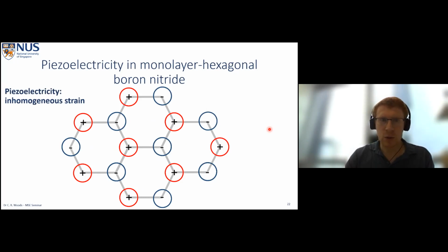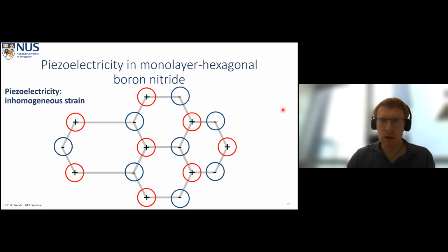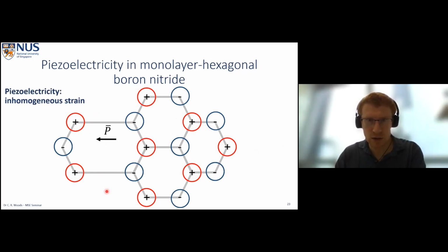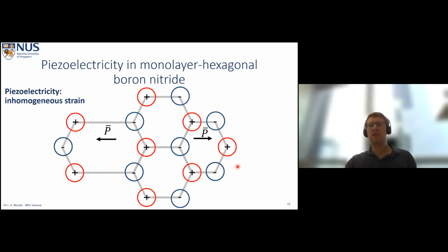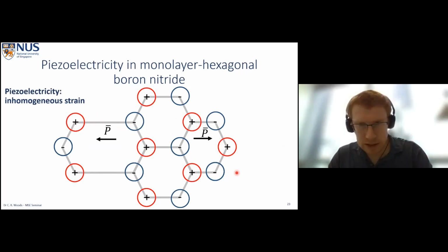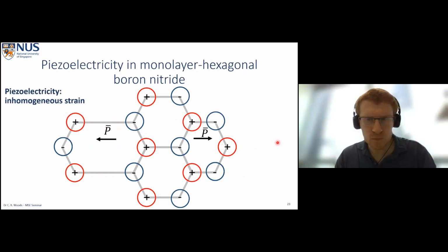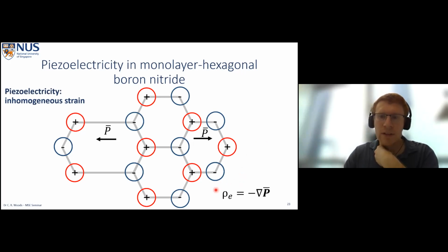So the way we're going to do this is through an inhomogeneous strain distribution. So let's use a simple example and create an exaggerated strain distribution across our 4 unit cells here. Something like this. So I've stretched this one. We have large expansive strain on the left-hand side, and then quite large compressive strain on the opposite side, and no strain in the middle. And when we do this, we can put some polarization fields on for our 2 strained unit cells. And what we find is on the left-hand side, we have a polarization pointing like this, but on the right-hand side, because we've changed the direction of our strain, we also switch the polarization around. So we created quite a large gradient in polarization here. And that gradient in polarization will give us an effective induced charge in our monolayer boron nitride layer.